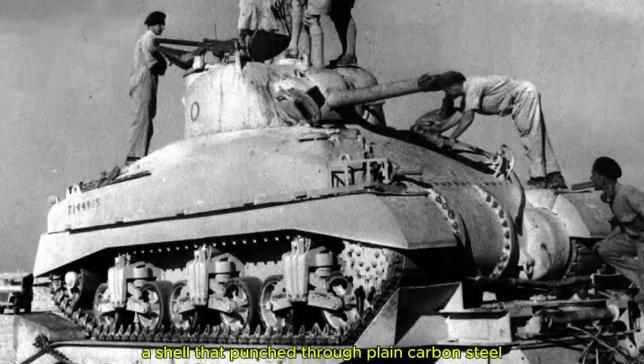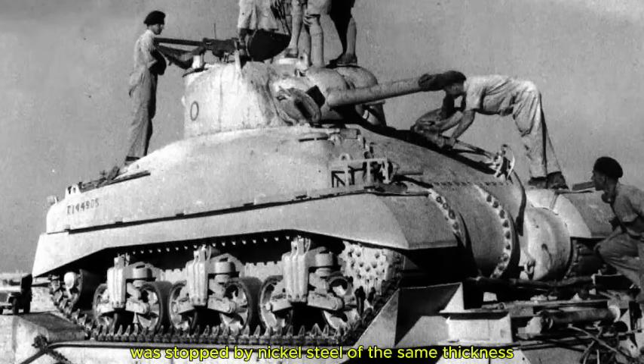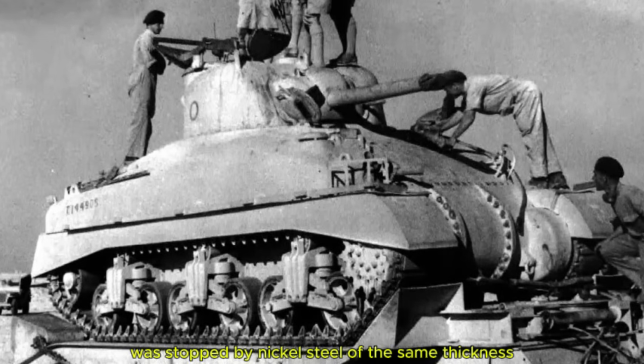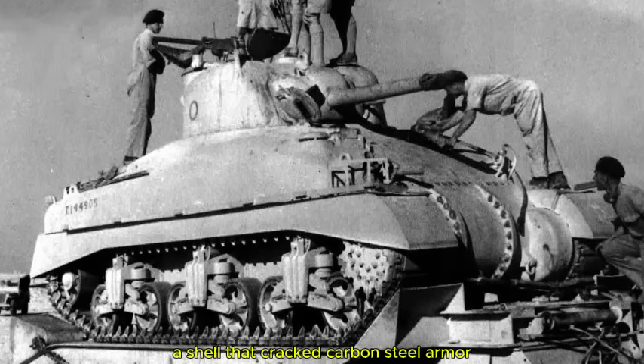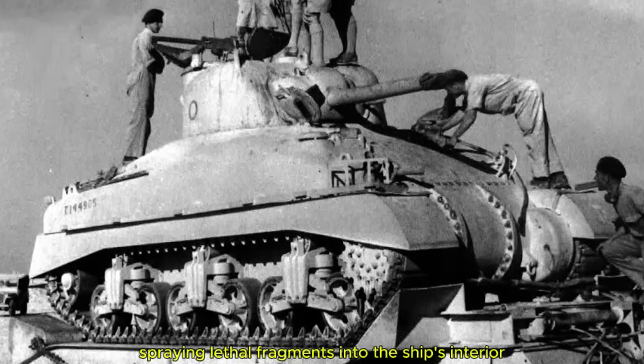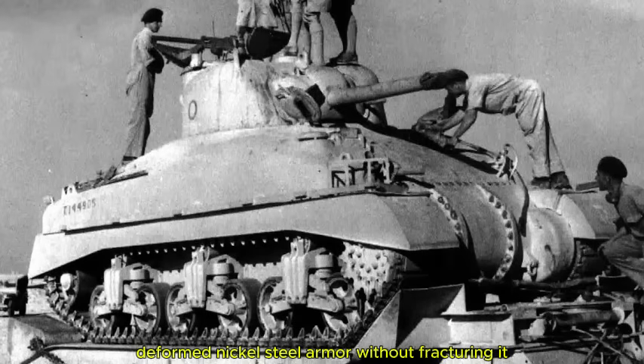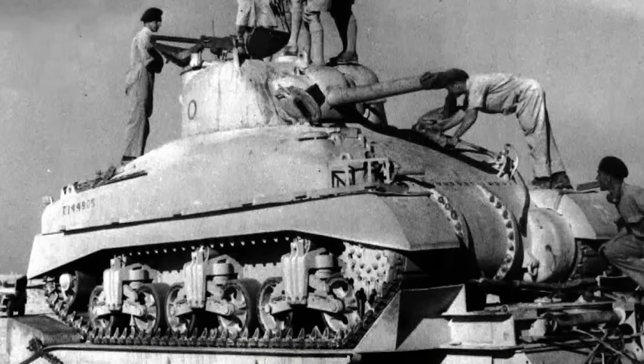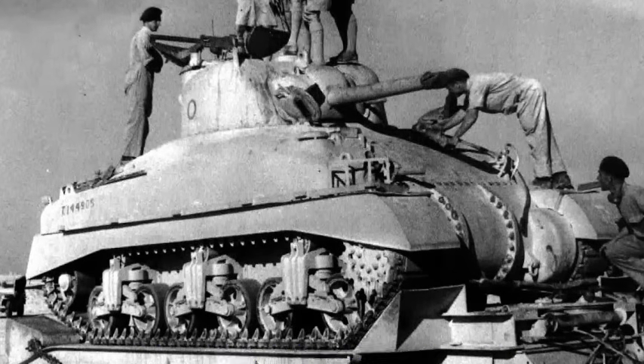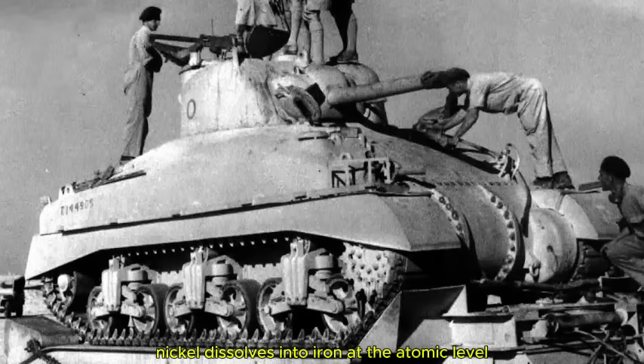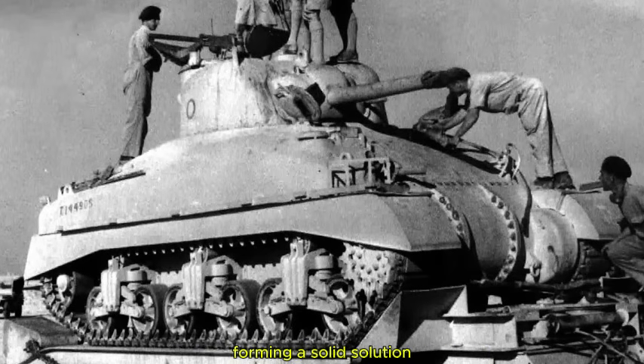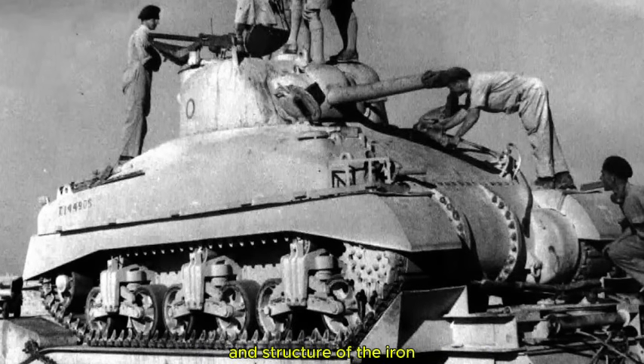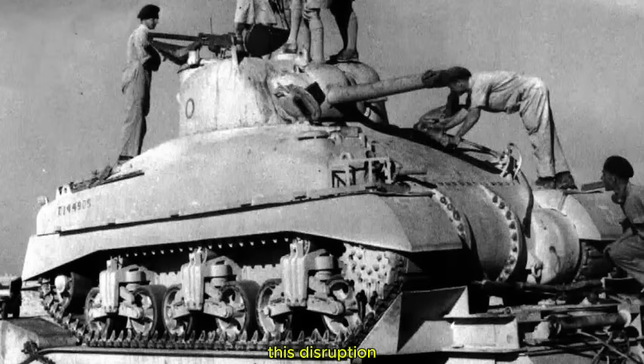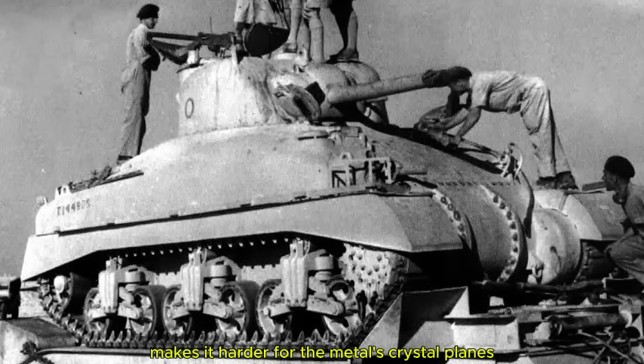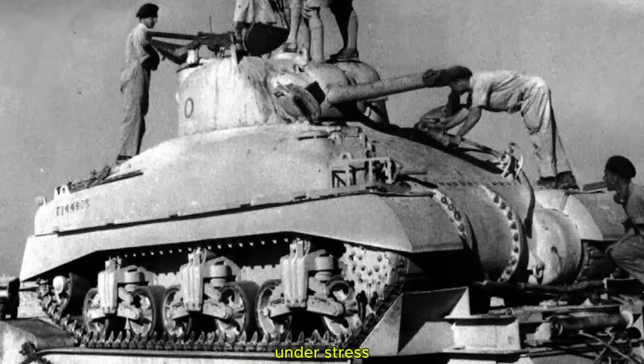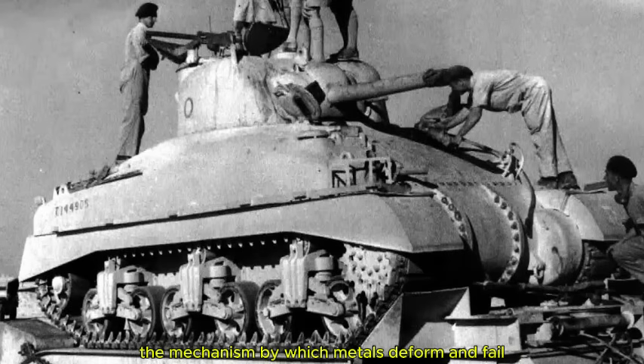A shell that punched through plain carbon steel was stopped by nickel steel of the same thickness. A shell that cracked carbon steel armor, spraying lethal fragments into the ship's interior, deformed nickel steel armor without fracturing it. The physics is straightforward. Nickel dissolves into iron at the atomic level, forming a solid solution that disrupts the regular crystalline structure of the iron. This disruption makes it harder for the metal's crystal planes to slide past each other under stress, the mechanism by which metals deform and fail.